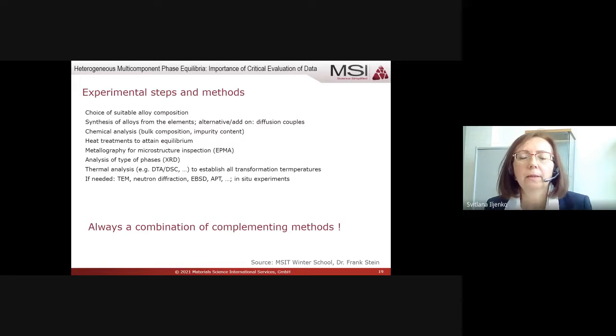If we look at the experimental steps and methods which scientists ideally apply in their research when they want to construct a phase diagram or find out just phase equilibrium, then it looks like that. So we start with choice of suitable alloy compositions. We continue with synthesis of alloys from the elements, or alternatively, there are other methods like diffusion couples. We make chemical analysis to find the impurities and to determine exactly the bulk composition of the ready material. The next step is heat treatment to get equilibrium condition.